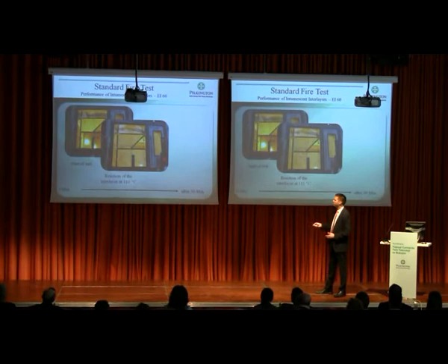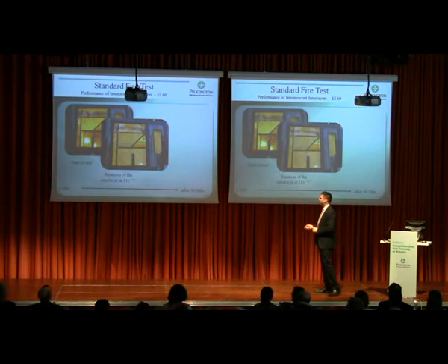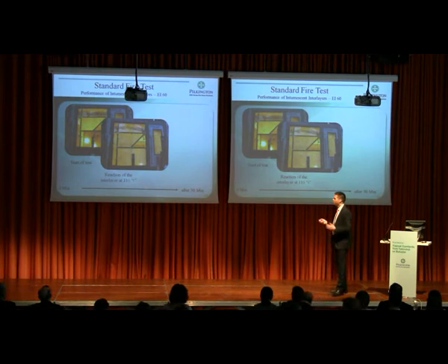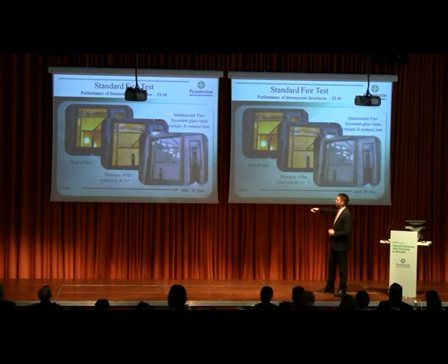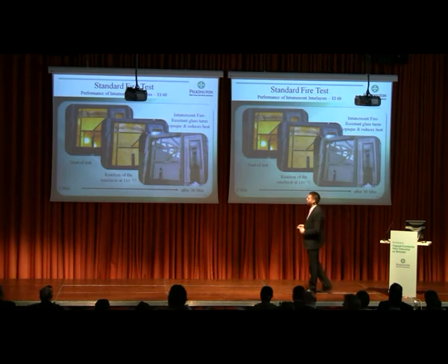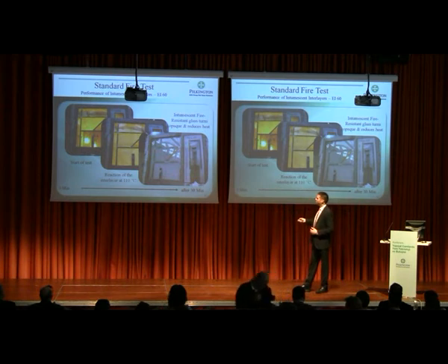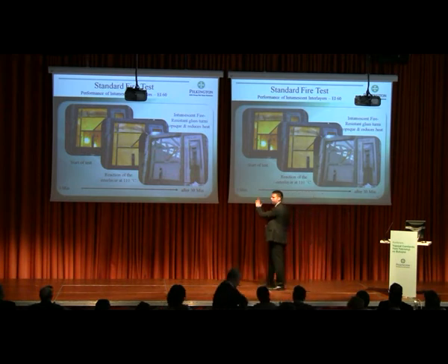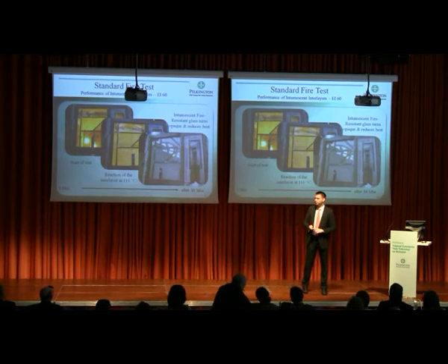After a couple of minutes it looks like this. All the first interlayers in the composition have started to react due to the heat in the furnace. The reaction starts at 100 degrees. 100 degrees in such a fire test is achieved after 1 minute, and then it goes straight up to 900 and 1000 degrees. If all interlayers have reacted, it looks like this. You won't see the furnace and the fire behind it anymore, but it's possible to stand in front of the pane and even touch the surface, so you are totally protected by such insulating units.